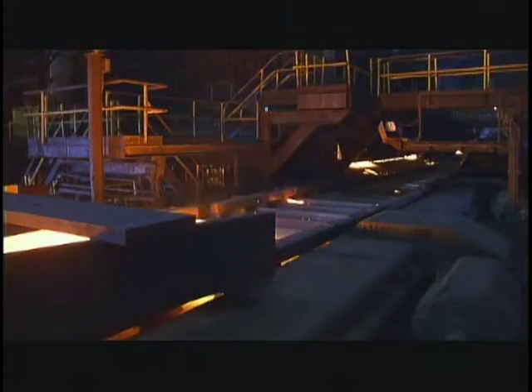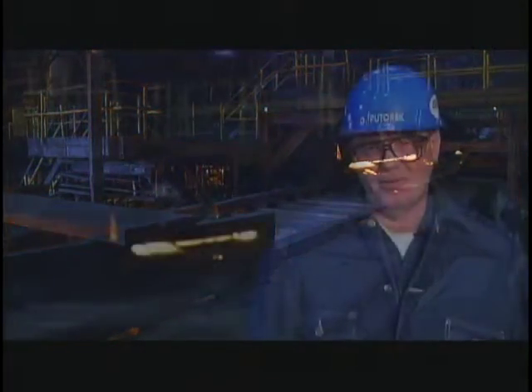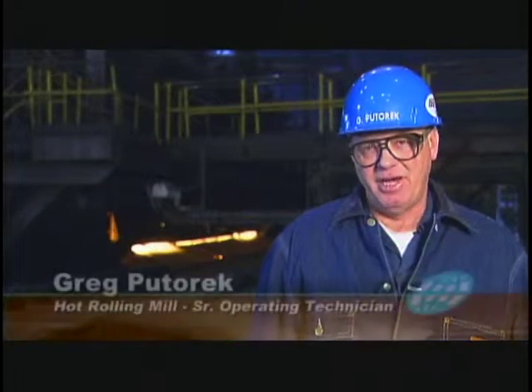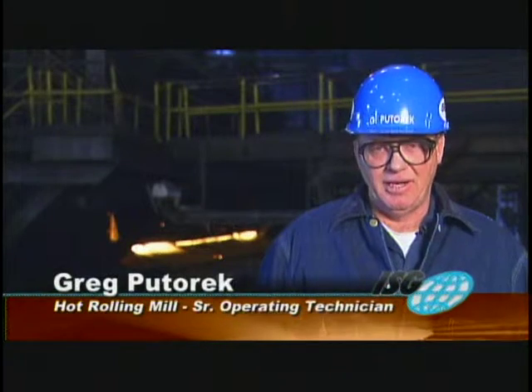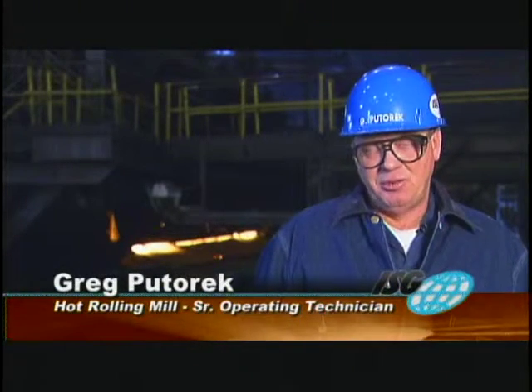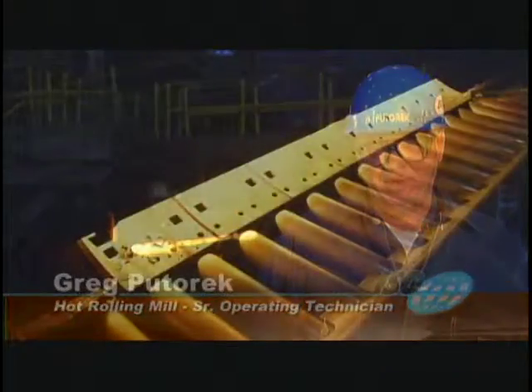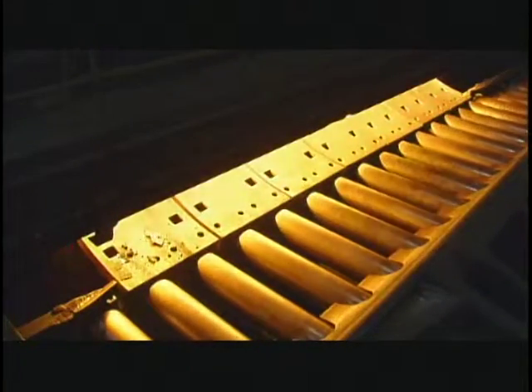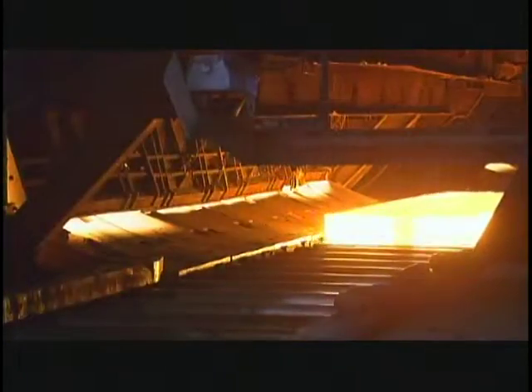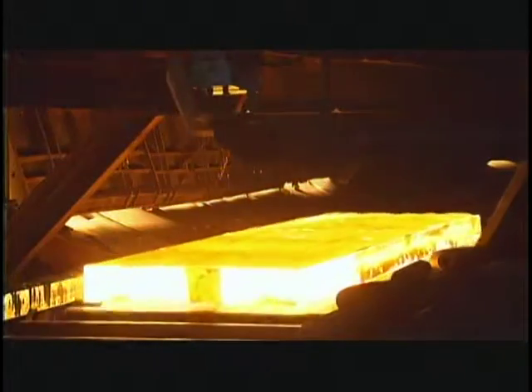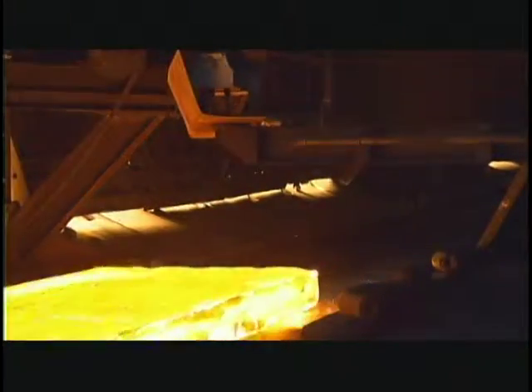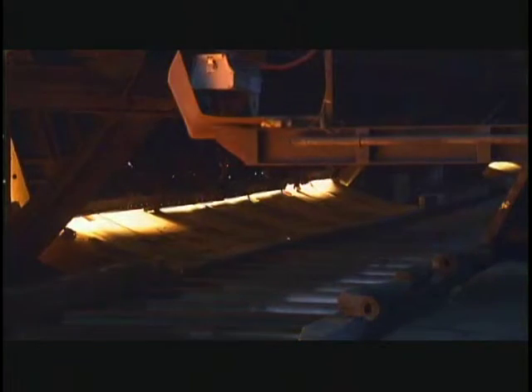We have 3 furnaces. Each furnace has a capacity of 750 tons. It takes approximately 2.5 hours to heat a slab. Our slab lengths range from 146 long to 384 long. Our thicknesses range from 8 inches thick to 10 inches thick. When we drop out of the furnace, we drop out at 2350. By the time it goes to R5, we shoot for 2020. We have plans in the near future to upgrade our furnace to extractors for quality purposes.